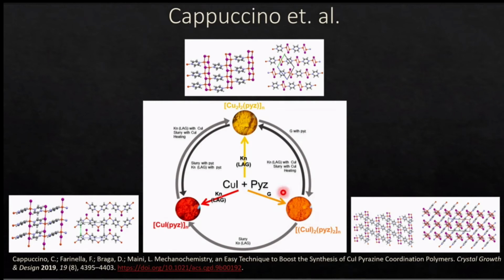Because then what they noted was that the orange polymorph would spontaneously decay into this red polymorph over here, and that this would happen over the course of about a week, which we saw in some of our samples. And we also noted that, as I said earlier, when you add the water, it immediately goes orange and then decays to red. So this matched our experimental results.